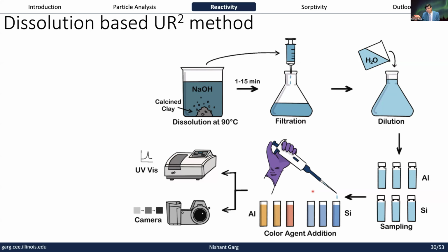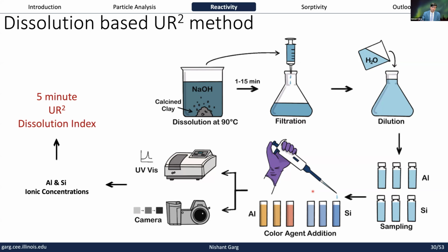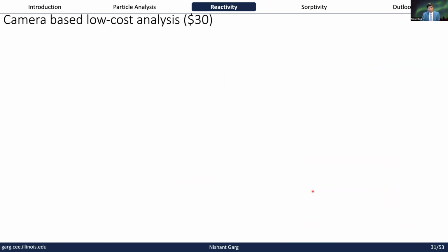The other thing is you can measure the concentrations of aluminum and silicon using an ICP, but the ICP tends to be a very expensive instrument, costing anywhere from 200 to 300K, and not everybody has access to it. So we wanted to also figure out low-cost ways to measure these ion concentrations. There we look at a very simple colorimetry-based method where you add certain coloring agents, and then you can use a UV-vis, which costs a few $1,000s, say $5,000, or you can use a $30 camera you can buy from Amazon, and just take a picture of your solution and get the concentrations in a very precise way. You combine these concentrations into what we call a dissolution index, which turns out to predict the performance reasonably well.